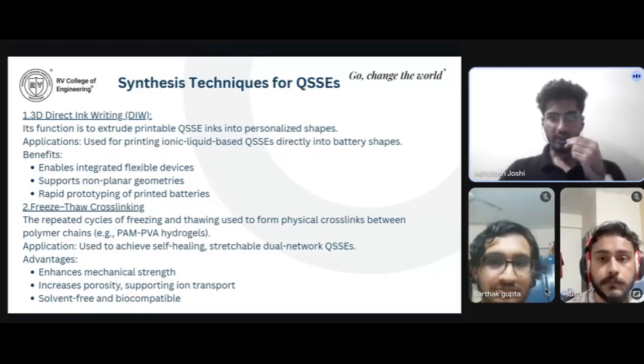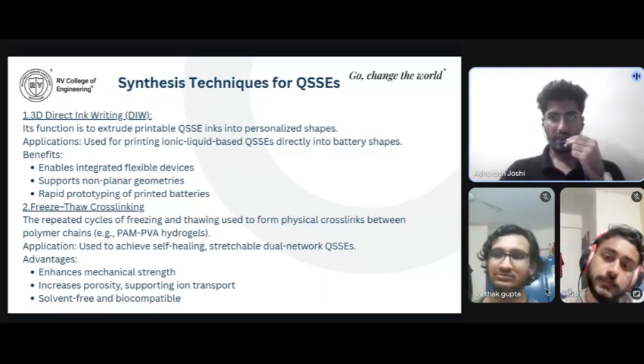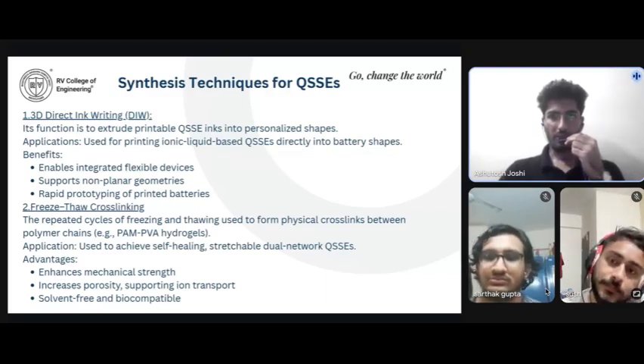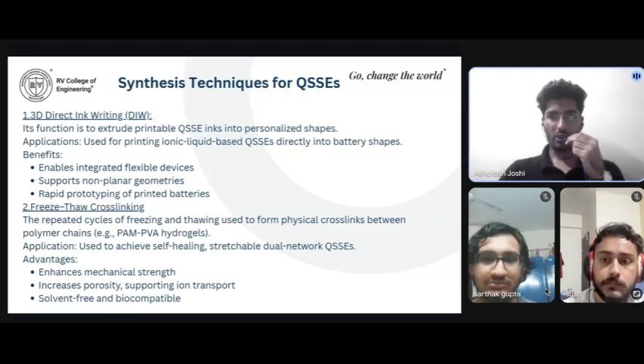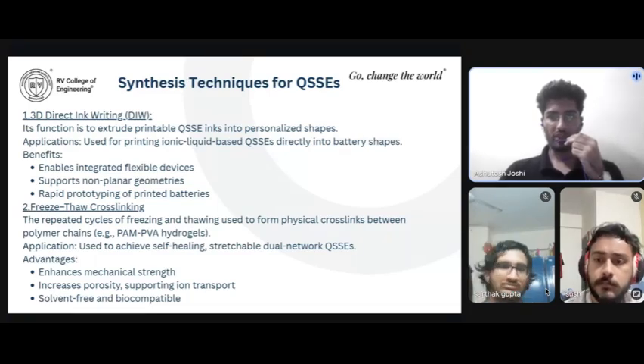With 3D direct ink writing, this is an additive manufacturing of 3D products that allows researchers to print customized QSSE structures using specially formulated inks. These inks are typically composed of a polymer matrix combined with ionic liquids or salt. In the DIW mechanism, the printable QSSE ink is extruded through a nozzle under controlled pressure and temperature. One major application is printing ionic liquid-based QSSEs directly into battery shapes. This is especially used for flexible or wearable electronics where battery designs need to conform to irregular shapes.